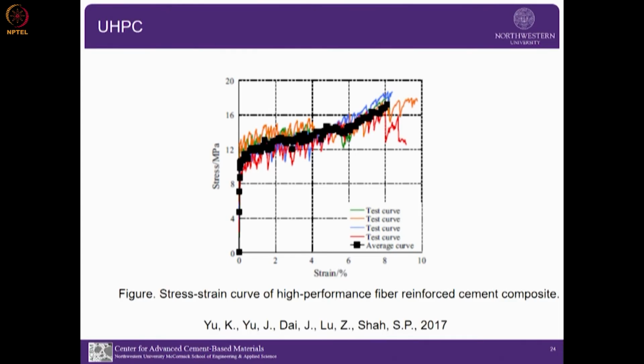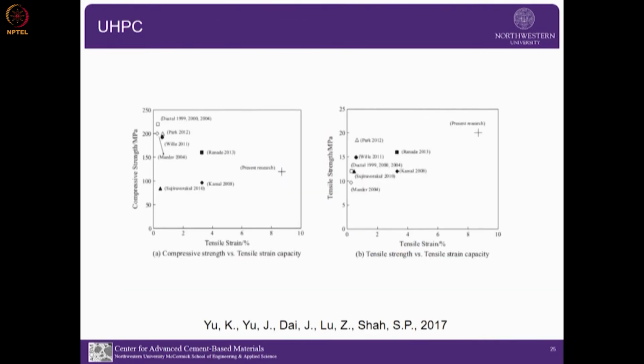You don't expect multiple cracking to have such a high peak tensile strength, as much as 16 megapascal. Because now we can control rheology, we can add these 2% volume of the fibers. And I thought it would be interesting, and we also put that in the paper.